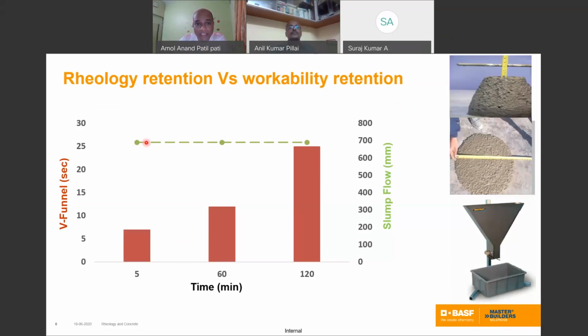First, this yellow line indicates your slump flow, starting from 100 mm to 700 mm. We are taking the flow of the concrete. The flow of the concrete at 5 minutes is around 700, then 680 or 690 at 60 minutes and 120 minutes. So these retain the workability for your placing, compaction, and finishing. I want to define the workability. So this is the workability retention.